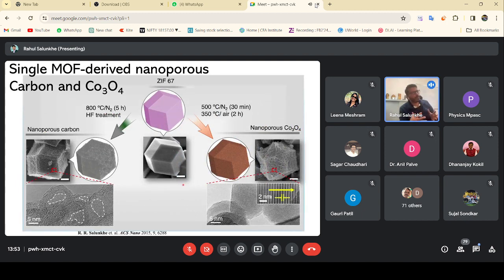In another interesting approach, we try to utilize this single MOF derived nanoporous carbon to develop two different materials. The interesting fact of our ZIF67 material is that if we heat this material in nitrogen atmosphere and provide an HF treatment, it leads to the formation of a nanoporous carbon material. And these nanopores are of highly graphitic nature, and these are the pores on the surface of the material. We can see that. On the other hand, if we directly heat our material in air atmosphere, the structure collapses. That's why we first retain this structure by heating this material in nitrogen atmosphere at an optimized temperature of 500 degrees centigrade, and that's how we can retain the shape of the original parent MOF.